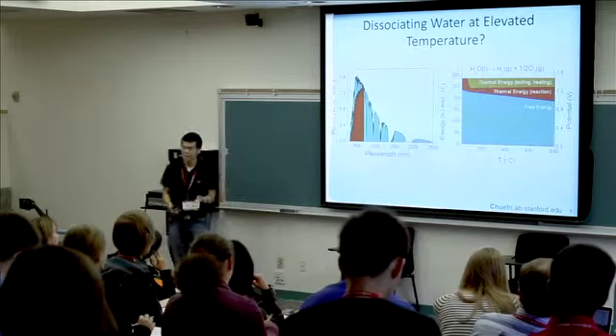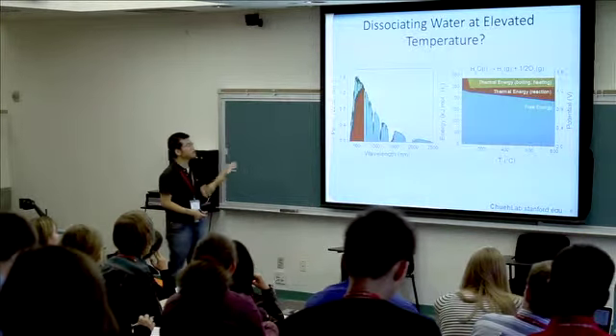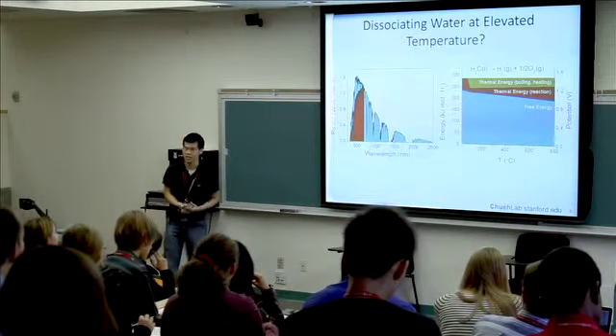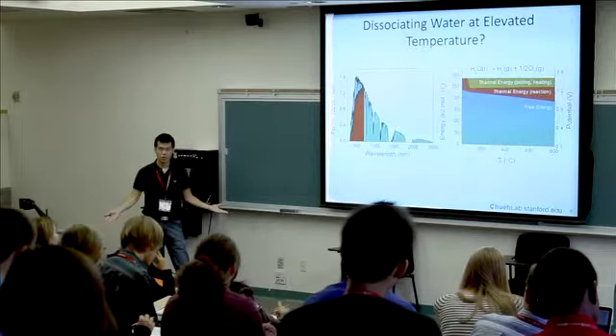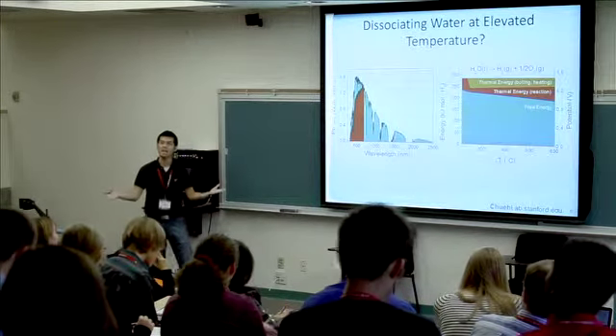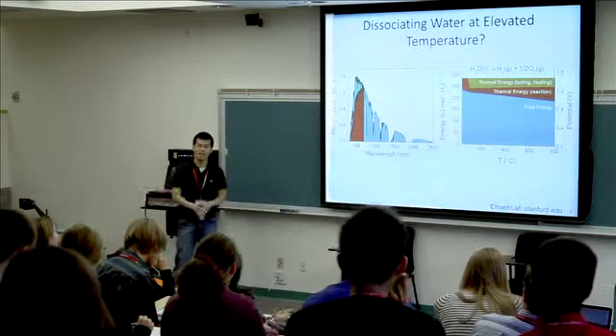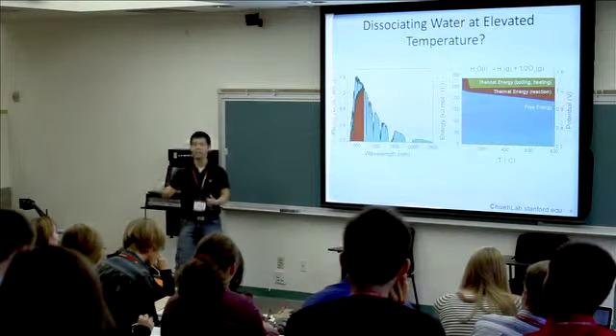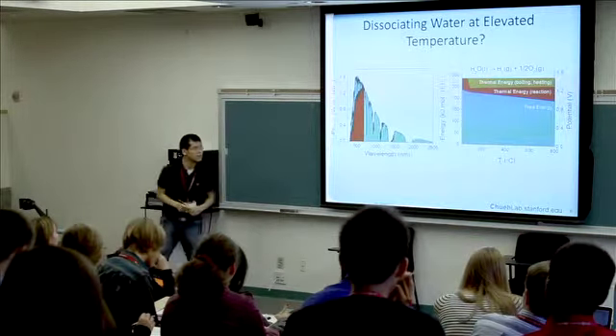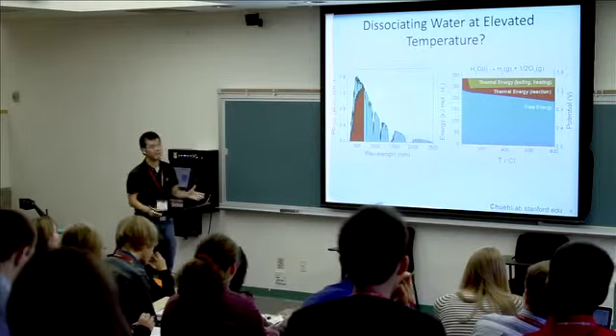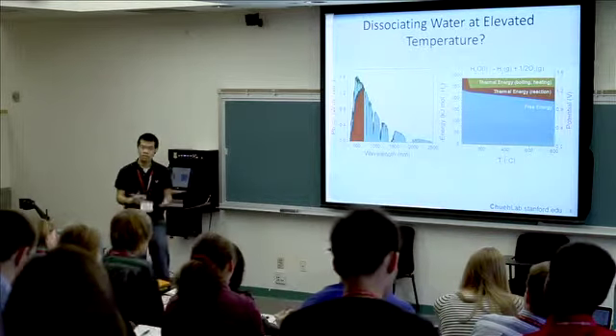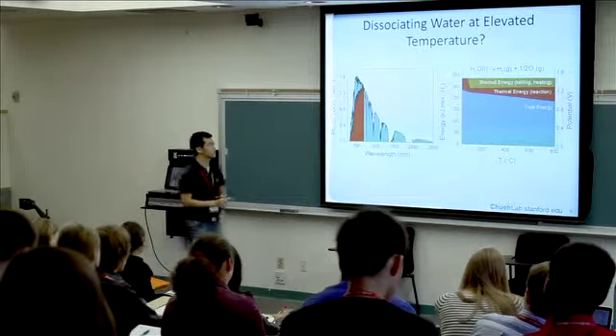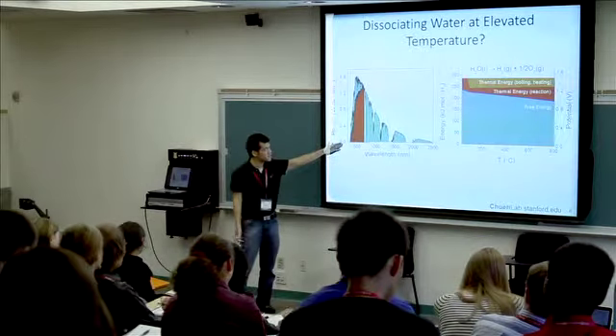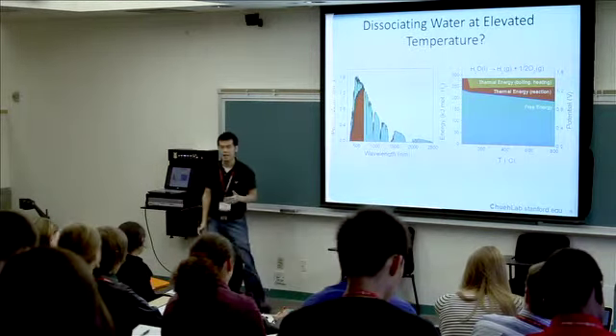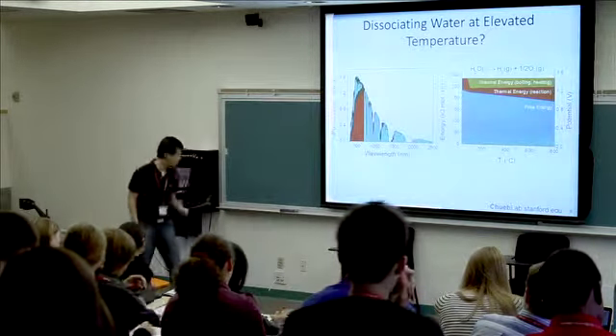So you gain a 20% thermodynamic efficiency, but you also get much more by using this to speed up chemical reactions. And let me say one more thing for those who might not be familiar with the temperature effect on chemical kinetics. So essentially what we're doing is we are making the atoms vibrate more vigorously. And this allows it to have greater probability of hopping over a particular barrier. So this is really the thermodynamic and the kinetic argument for increasing the temperature of water dissociation. And as you can see, we have a better chance at utilizing the available solar spectrum.